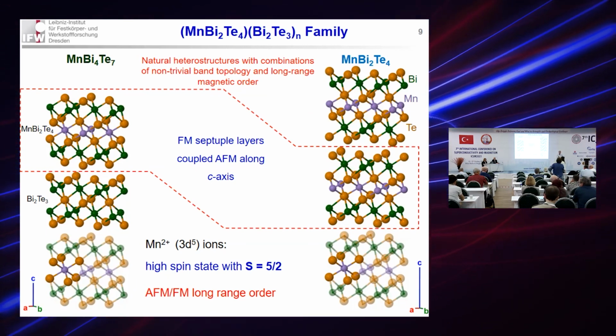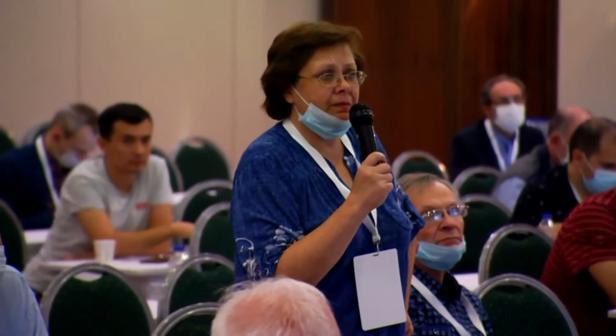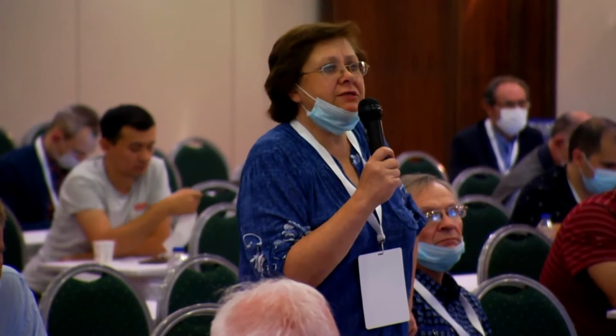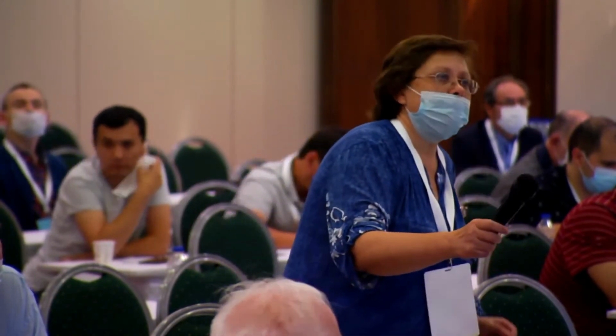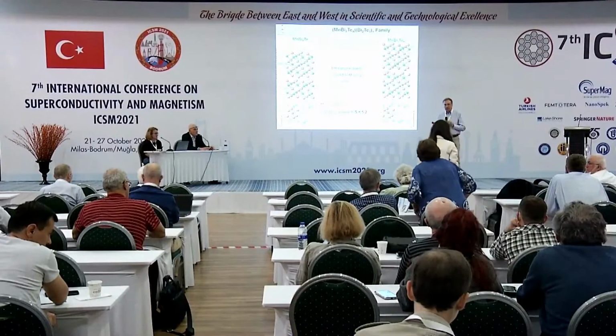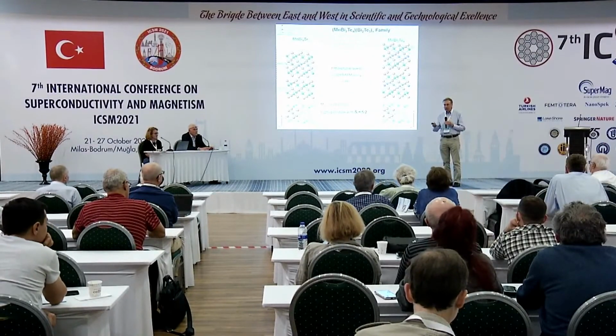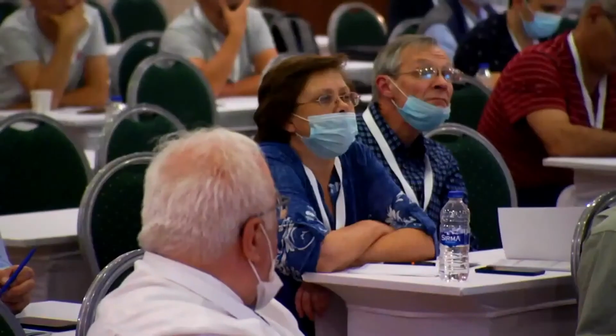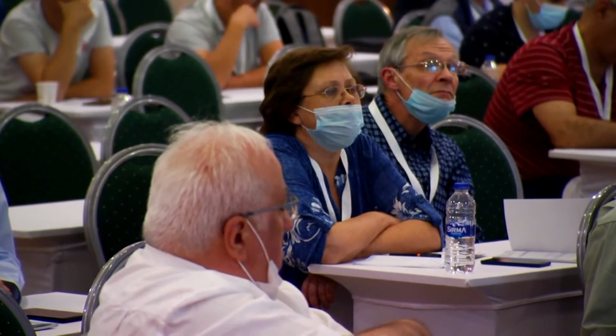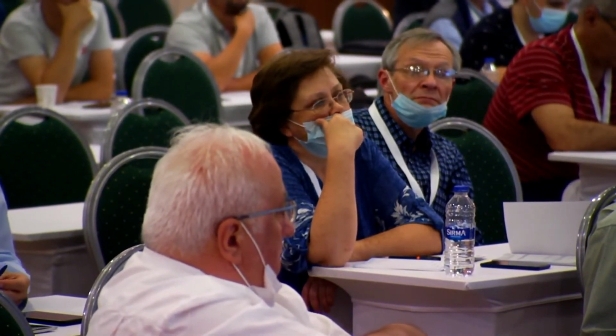At the beginning, you mentioned XMCD, magnetic dichroism. Which results did you obtain with magnetic dichroism? Oh, yes. That was a very important experiment. That's a very good question. Because the gap is on the surface, but the magnetism is in the bulk. The question is whether this magnetism, the ferromagnetic magnetization, is present at the surface of this sample. This is not that obvious. It could be some surface defects or degradation or whatever, which suppress the magnetization of the surface layer. For that, we made this XMCD experiment, X-ray magnetic circular dichroism, which has a very small penetration depth, and we definitely see magnetic signals in the samples which show this gap in the Dirac cones.